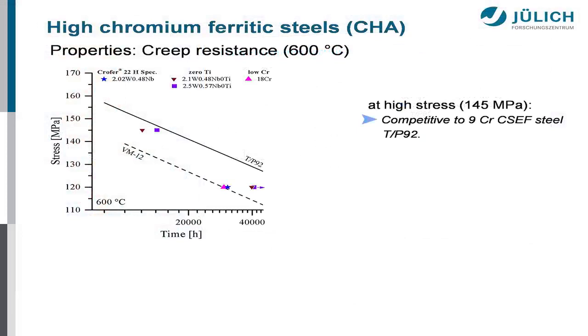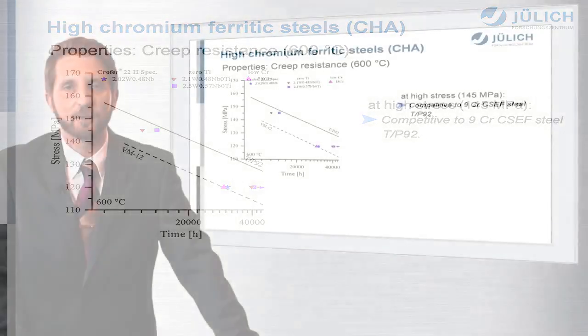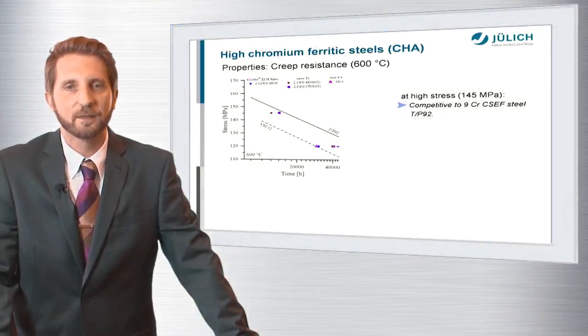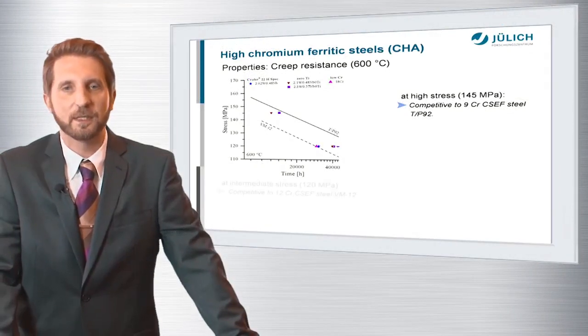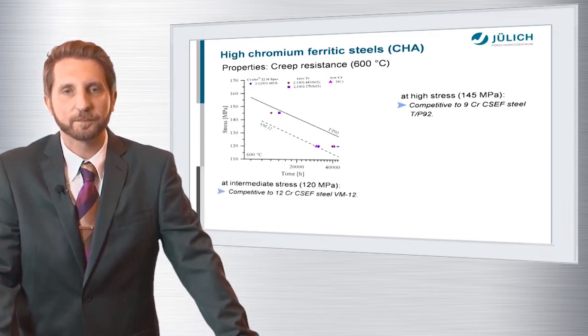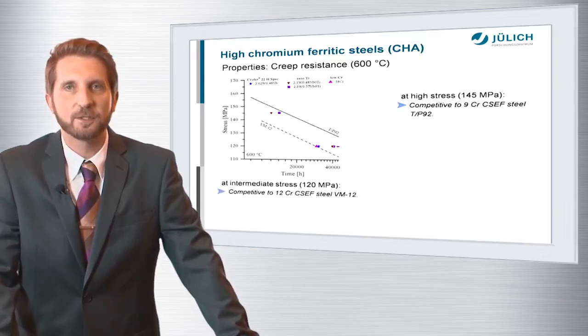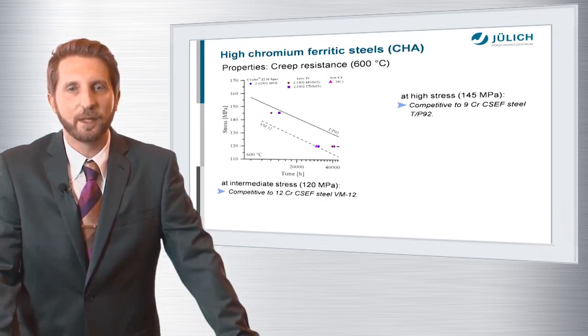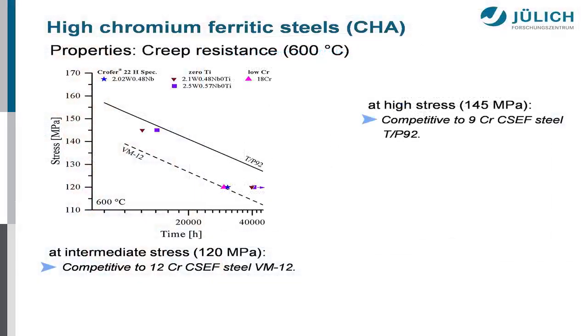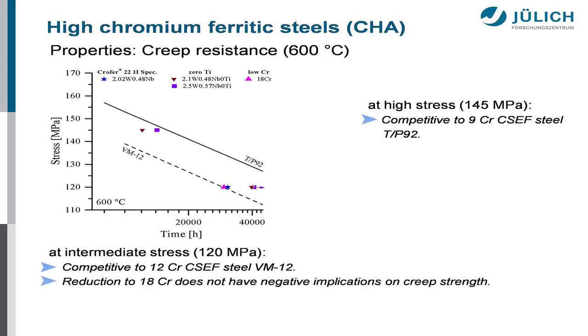If we compare the creep performance of these trial alloys to ferritic martensitic grades to benchmark this, we will see that at a high stress level of about 145 MPa, the higher tungsten and niobium alloys are competitive to the 9 chrome grade TP92, which is the benchmark today in power plant application. At an intermediate stress level of about 120 MPa, the baseline composition, the Crofer 22 composition, is still competitive to the most steam oxidation resistant 12 chromium ferritic martensitic steel VM12, and the higher tungsten and niobium content materials perform much better.